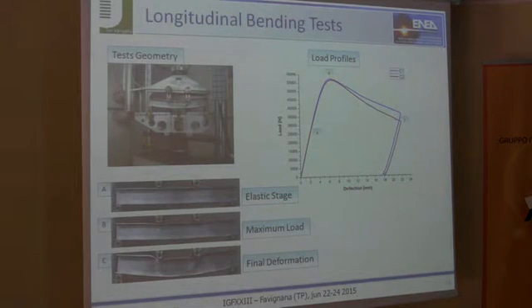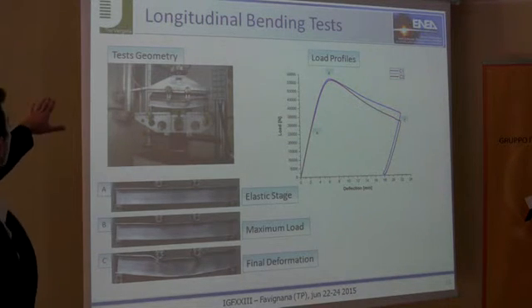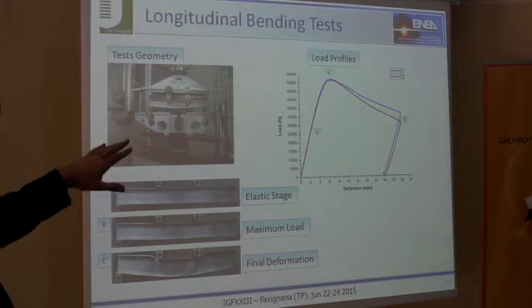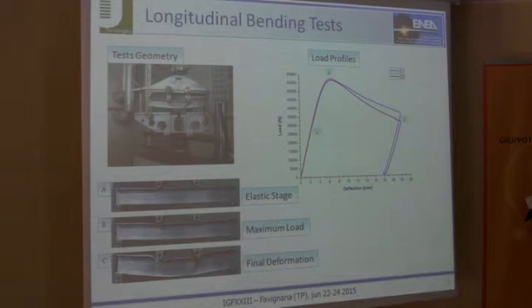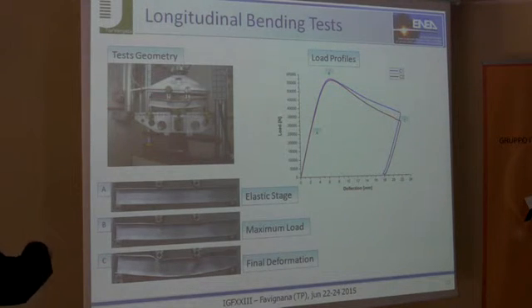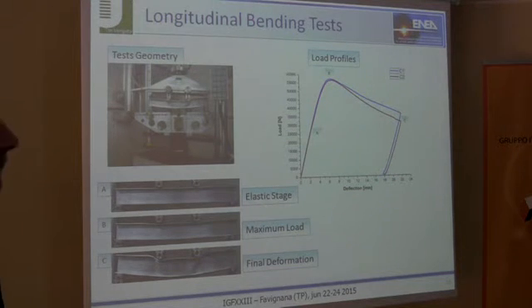The results of the longitudinal bending test. In this figure you can find the test geometry, and in the graph the load profiles for 2 samples. The trends are very similar, with a first linear elastic stage until about 45 kilonewtons, and then you can see a global plastic deformation until the maximum load value of about 58 kilonewtons. And then a reduction of load occurred by plastic local deformation at the punches regions.